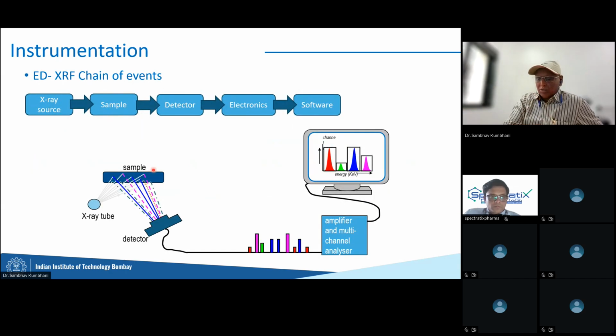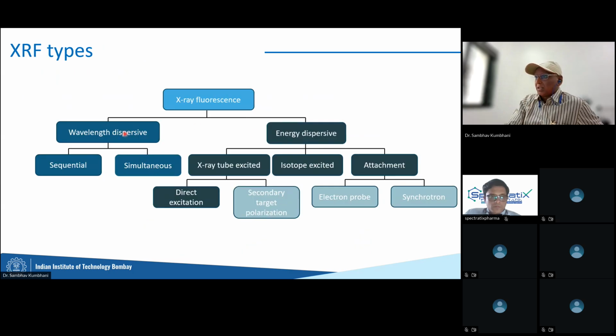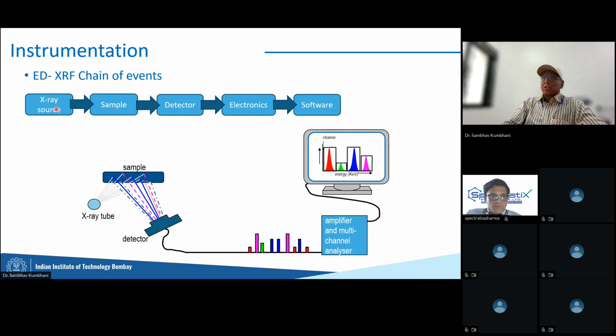Here's the instrumentation. So what I'll do is primarily focus on the two main techniques, the most common instrumentation patterns of both these machines. So for EDXRF, you have a source, you have a sample, you have a detector, and then you have electronics and software to show what is actually measured. It's pretty straightforward. An X-ray light of a very specific wavelength hits the sample, causes different elements within the sample to excite and release fluorescence. So one wavelength went in, multiple wavelengths came out, blue, pink, green came out. And the detector separates the colors out, or the peaks out. And based on each color, we can say that this is aluminum, this is copper, this is nickel. So this is a bronze alloy, for example. So this is how XRF works.